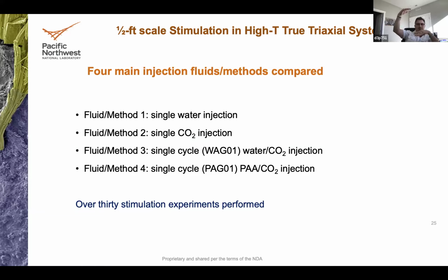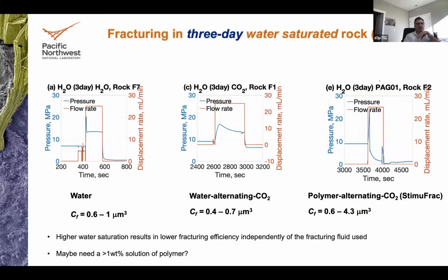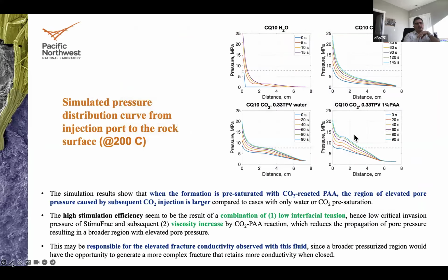You start building viscosity. You're correct. That viscosity may reduce the mixability of the fluid, but at the same time, these fluids, due to the very low interfacial tension, may have already mixed. So what the viscosity increase does is reduce the leak off of CO2 into the formation, and you get these pressure envelopes that you saw in the simulations. What we think is that the combination of the low interfacial tension that enables miscibility of the two fluids, together with the increasing viscosity that prevents leak off of CO2, is what generates these large fractures. But again, this is just a hypothesis.